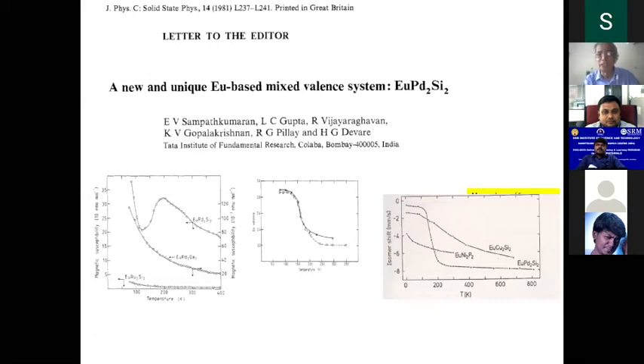The reason is the following. I already showed you one example, europium copper silicon, which was the first europium material with valence change, discovered by an Israeli group. The second material is europium palladium two silicon two, which I show here. As a function of temperature, you could see a very huge change in the isomer shift of europium. It's a very sharp change. Such a sharp change was never observed before. Even today, no material was found to exhibit such a sharp change in the valency. The isomer shift is a measure of the valency here. What I plotted is the isomer shift measured by Mössbauer. We can treat it as a valency. Here this is the 3+ state, this is the 2+ state, a very huge valency change.